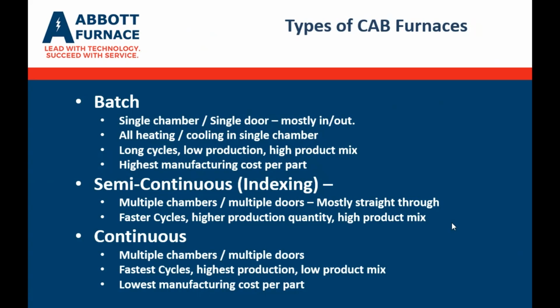And then the continuous furnaces, which most people are familiar with, can have multiple chambers for the different processes that we saw. Many doors, they have the fastest cycle with the highest production and low product mix. A lot of these furnaces are running 24/7, 50 weeks a year. In some cases, they're running the same parts or very few product mixes and very high quantities of each of those parts, where recipes may simply need to be changed, whether it's heat or belt speeds. The continuous line produces the lowest manufacturing cost because it is a continuously moving belt that, once it's stabilized, makes it pretty easy to keep the atmosphere and temperature at a quality level.